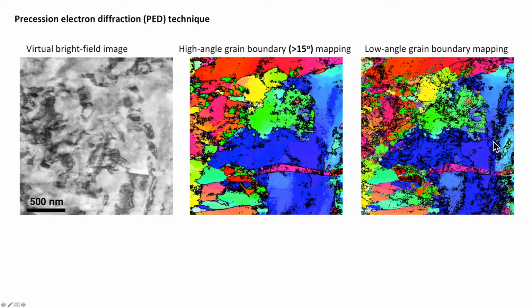In the virtual bright field TEM images, they correspond to the dark grains. What this tells us is those nano grains we observed in the bright field TEM image as well as the virtual bright field TEM images are not separated by the conventional high angle grain boundaries. They are separated by the low-angle grain boundaries. What this means is that those nanocrystalline grains are not formed by the conventional dynamic recrystallization mechanisms, where the dislocations accumulate and new grains of a brand new orientation form in the microstructure. Rather, it's a top-down grain refinement process. The formation of those nanocrystalline grains is not a result of heat, but more a result of the crystal fragmentation.